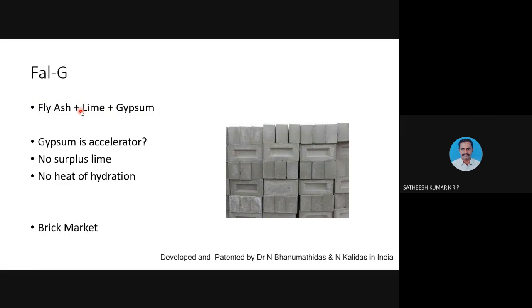Contrary to the hydration process of the Bogue compounds in cement, in this FaL-G combination, no surplus lime is left behind, and no heat of hydration is liberated, because the fly ash reacts with lime with the gypsum as an accelerator. So this does not involve any heat of hydration. This reaction is also pretty fast. It has a much shorter curing time than conventional concrete.